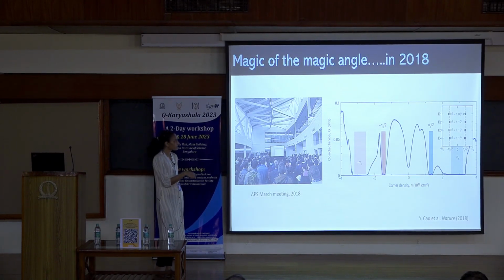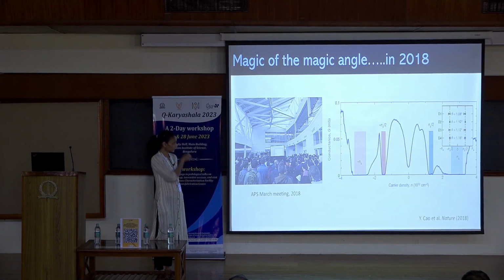Earlier, in the previous graph, I showed you resistance as a function of gate voltage. This is the same graph, but they used conductance as a function of carrier density. So if I were to convert my previous graph, my resistivity peak would be a dip. Okay, so take it to be that way. So in graphene, you would have had a single dip in conductance as a function of density. Sorry, so this is my charge neutrality point.